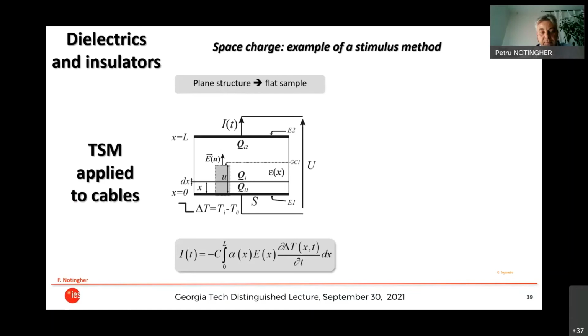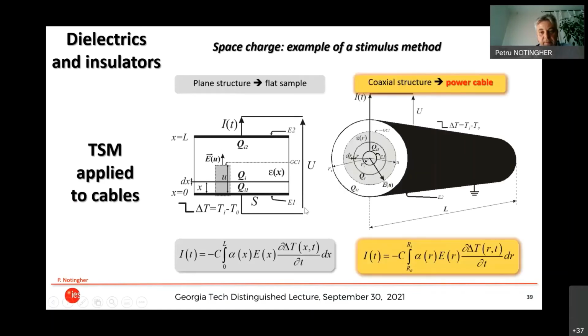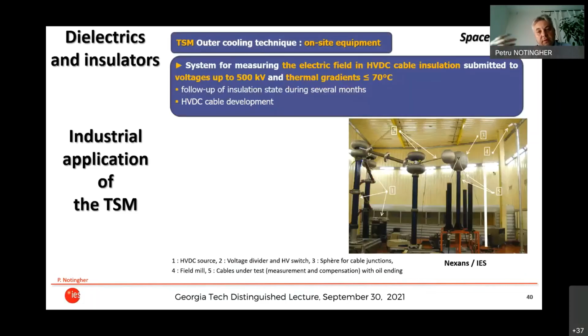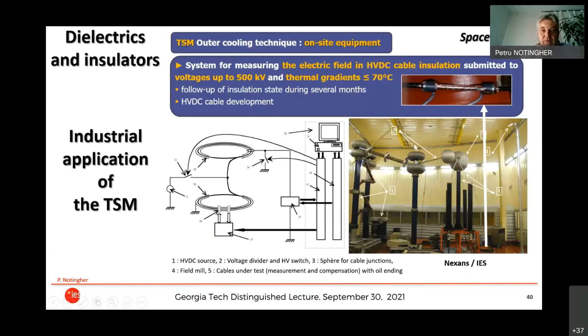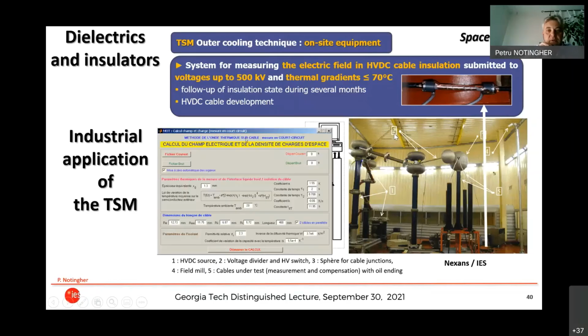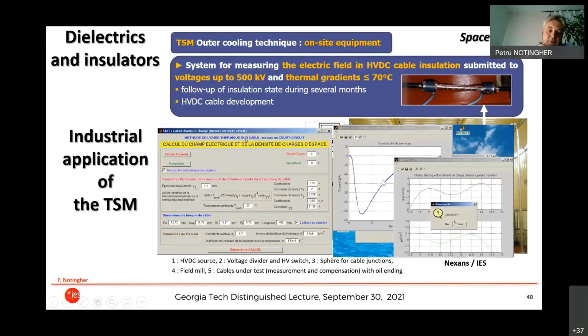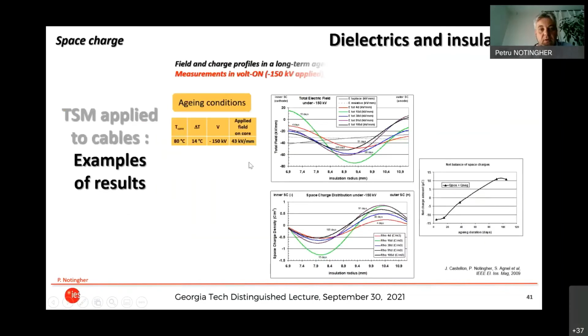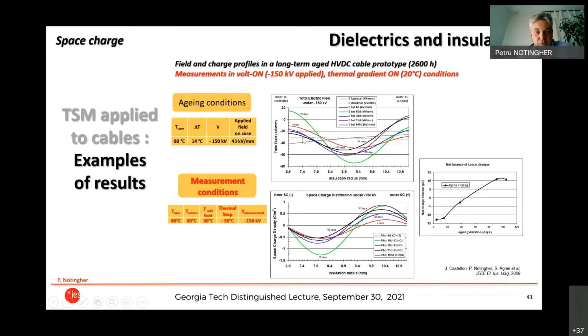So you can apply the same principle, which is here for the flat structure, to a cable, and then you'll have the field with respect to the radius. And you can, of course, build industrial installations which will help you to qualify the cables and the material for the cables for an industrial use. So here is an example of currents that are measured and then field distributions that are measured on cables in an industrial facility. And here are some examples of what you suppose the distribution to be in a cable. So either a capacitive one or a resistive one, but in fact you have neither one nor the other. You will have fields that can be much higher than the one that you expect.